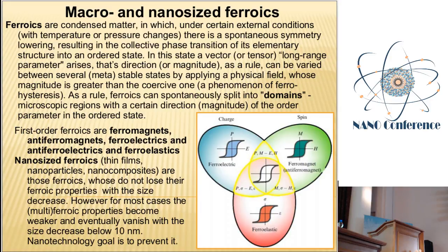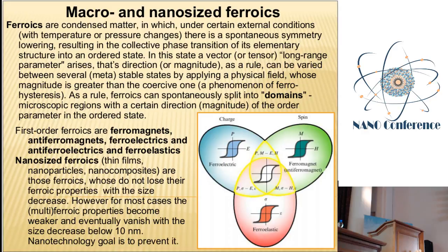But the problem is, when you go down to the nanoscale, you decrease the size either of the layer, the thickness of the layer, or the size of nanoparticles. Typically, there is some critical size below which properties like long-range ordering should not exist. This may happen for very many reasons. The first reason is that there is too small an amount of atoms remaining, and the system does not have enough force to establish cooperation between them.